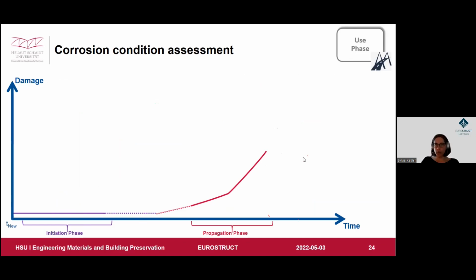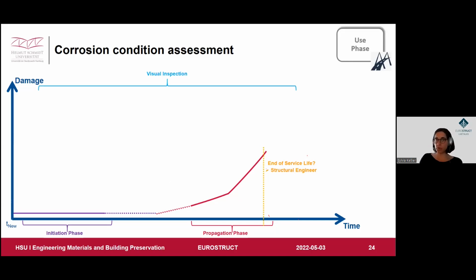And what we always should do, even though at the beginning it doesn't give any clue, is visual inspection. And as soon as we see anything like cracks, we need to involve a structural engineer to be sure that the reliability of the structure is still in good shape. It's the very beginning. What is really helpful? What kind of parameters, what data?